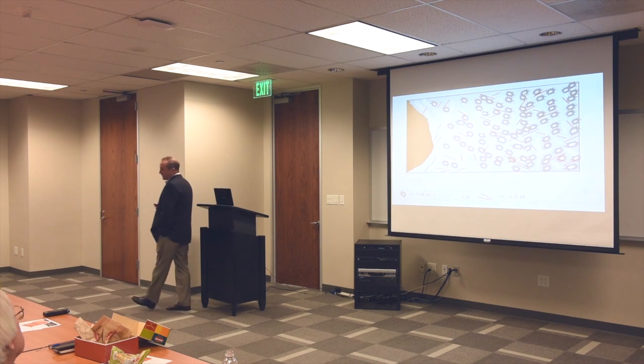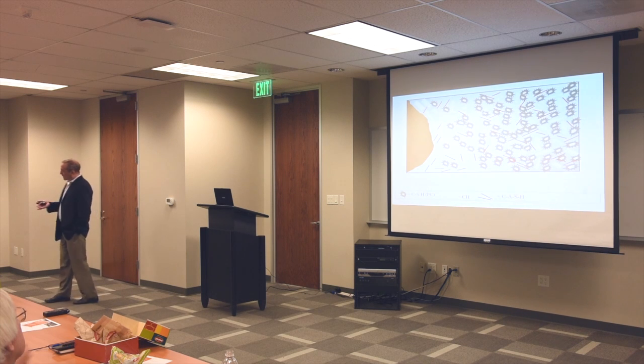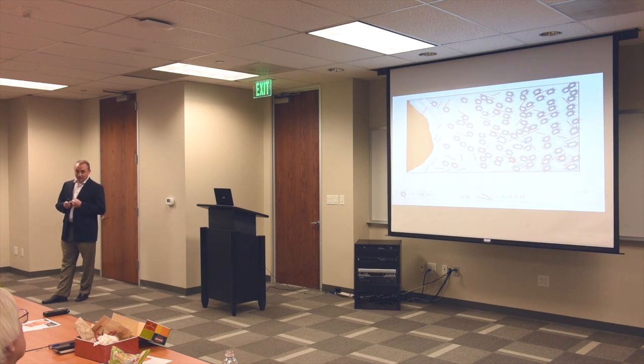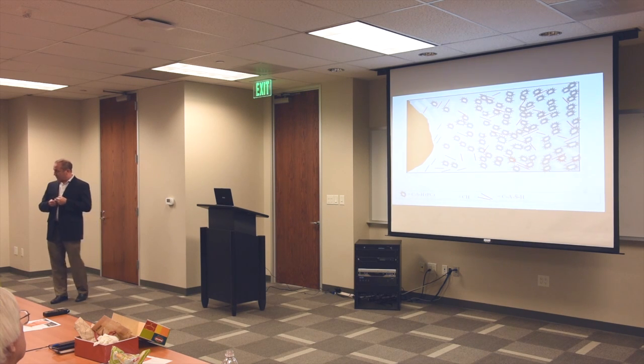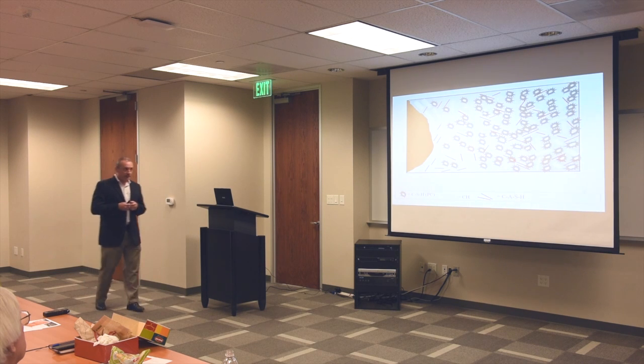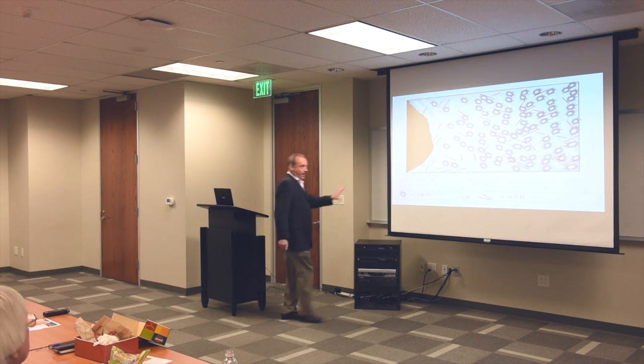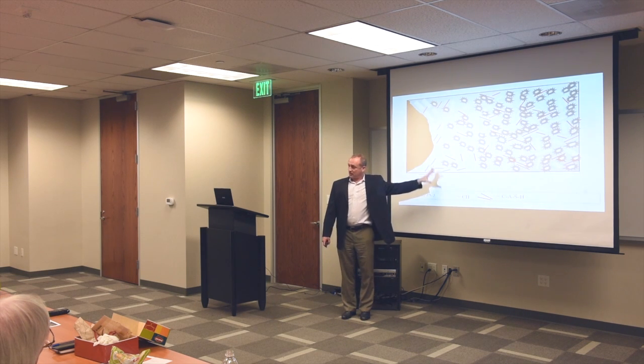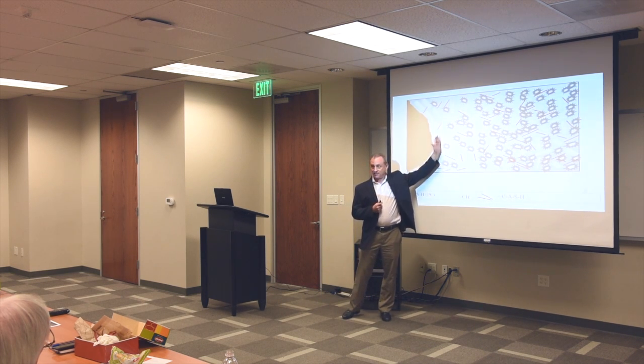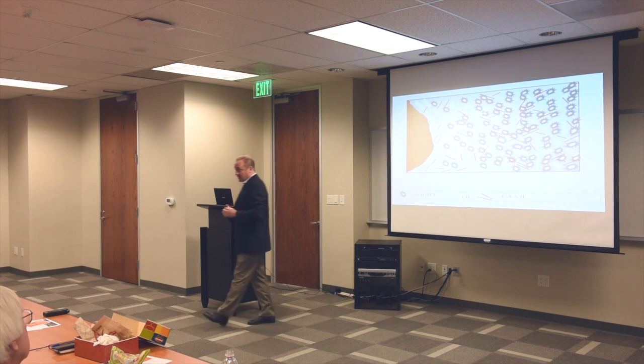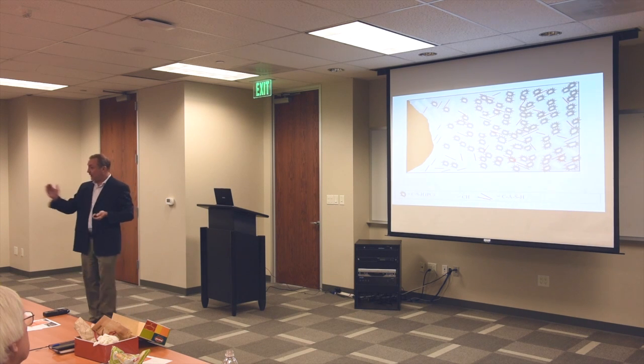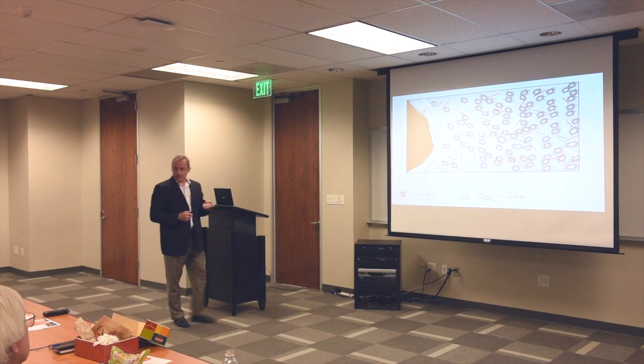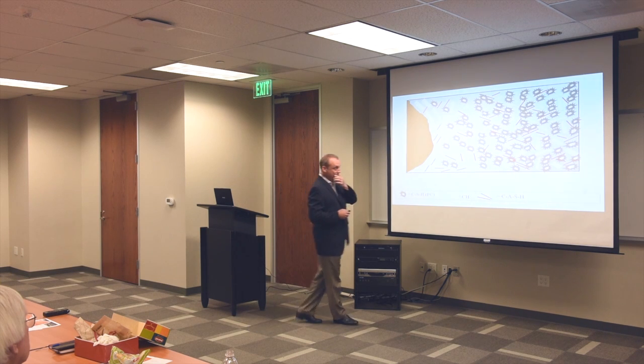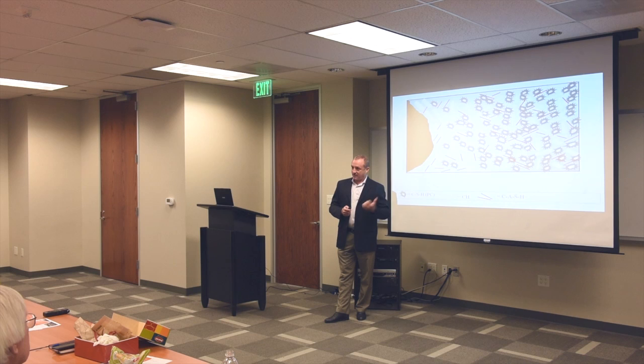The other problem with concrete, where these materials help as well—for any of you who have worked with or tested concrete, we know it often fails when loaded around the coarse aggregate particles. This is a region we call the transition zone. It tends to have a higher water to cement ratio, and a lot of crystals that tend to align themselves in a preferred manner, which means that under load, the crack will travel right through the interface. If you put this concrete out in a marine environment, the vast majority of the water and salt will actually travel around the aggregate particles because it's the path of least resistance. In many ways, this is the Achilles heel of concrete—this weak link between the rock and the surrounding paste. There's not much we can do with a straight cement mix to remedy this problem.